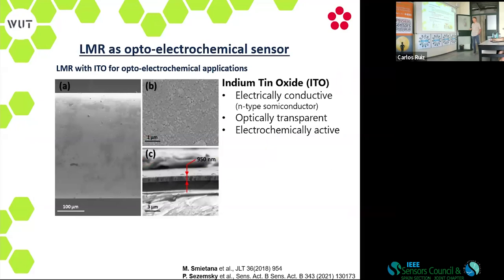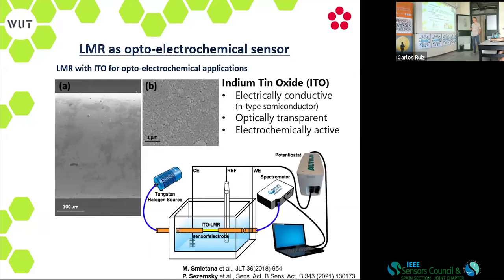But the most important thing is that when we apply some materials, one of them is indium tin oxide, but there are some other materials that we will tell you about later. On top of optical transparency, they have good properties for LMR that can also be applied. So it can be used as an electrode at the same time. ITO is one of them, an N-type semiconductor, optically transparent. A piece of multimode fiber was connected to the light source in a transmission configuration, and then coated with ITO. Electrodes, you can see here three electrodes.